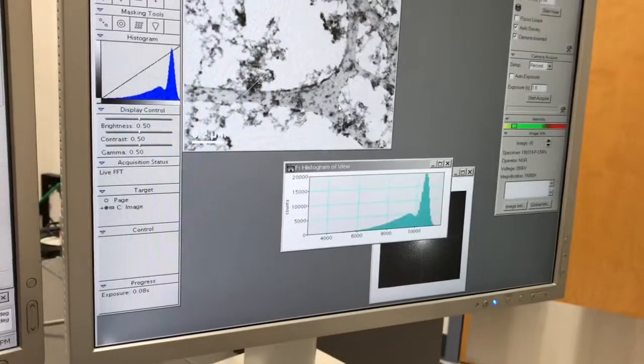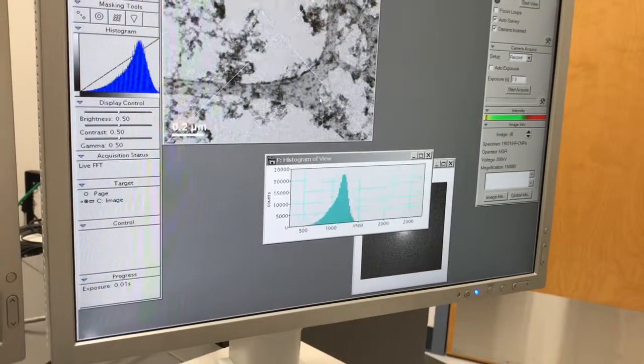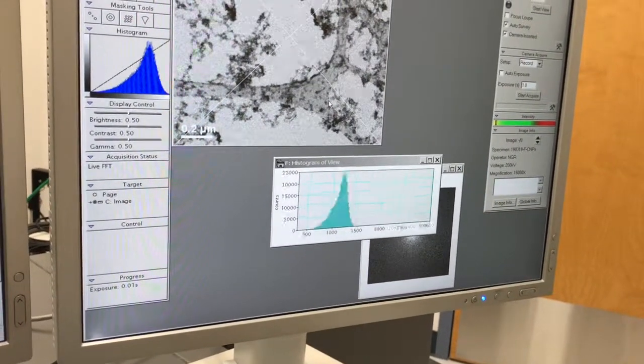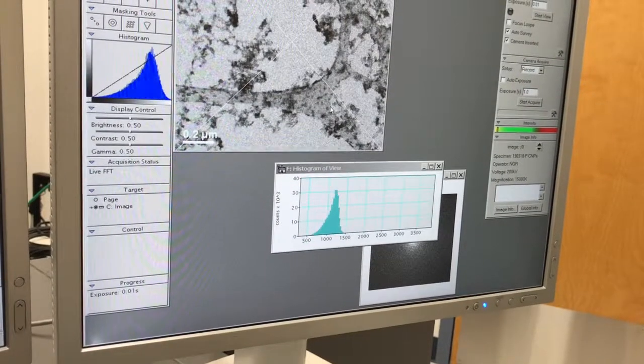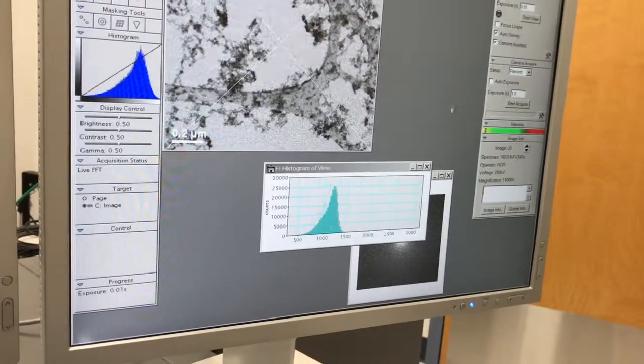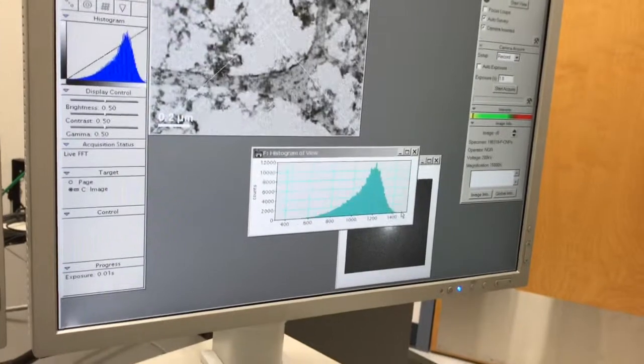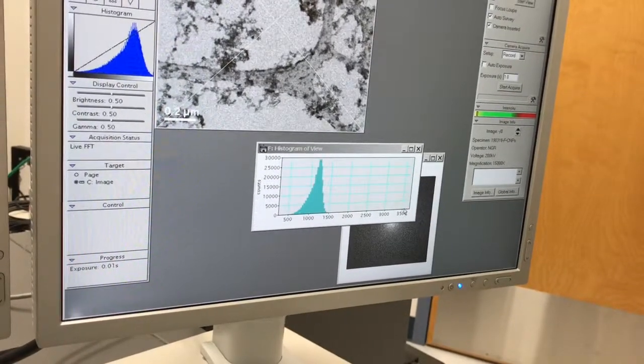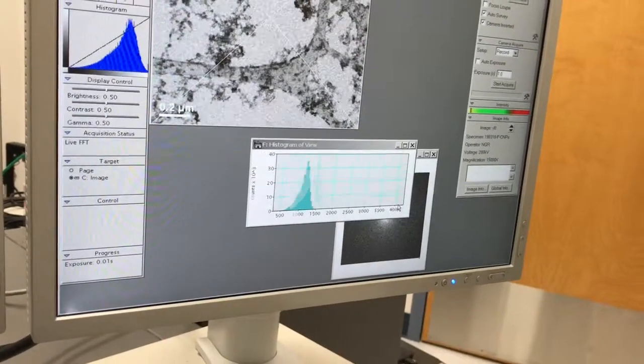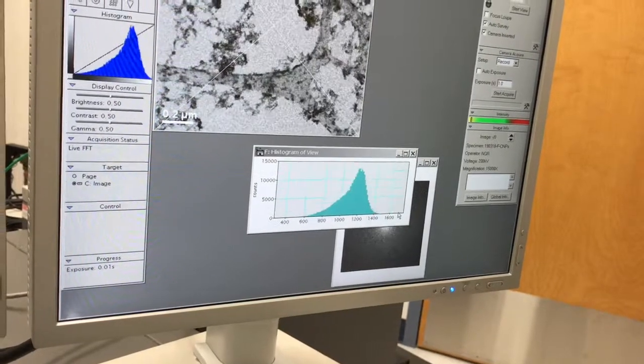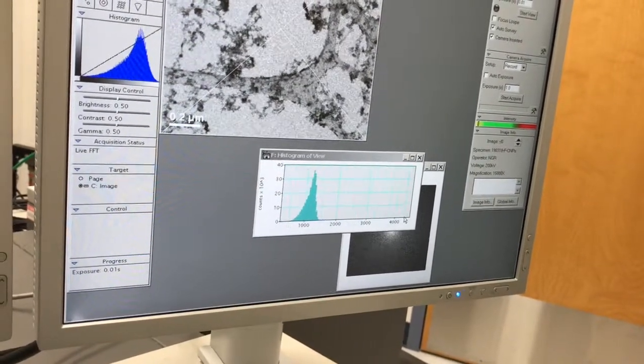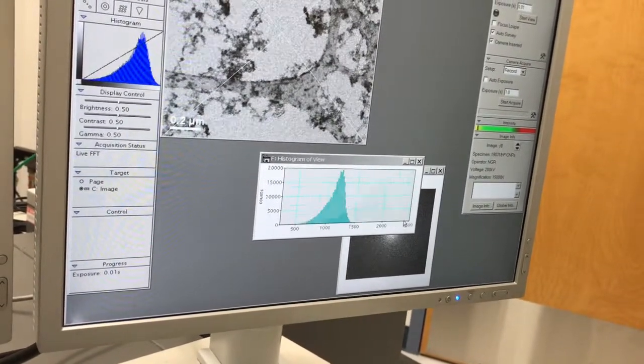If I go back down, I'm at 0.08. If I go back down to 0.01, you'll notice my max grayscale value went down, because the max signal went down. So that max grayscale value is linearly, approximately anyway, linearly scalable with exposure.